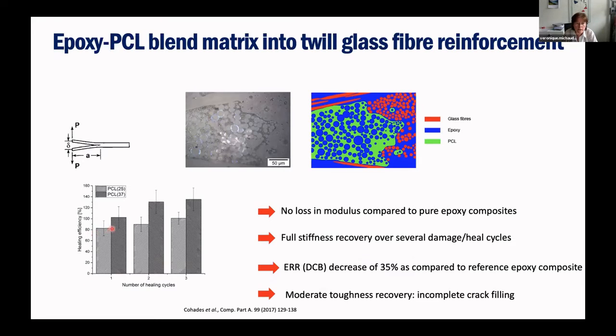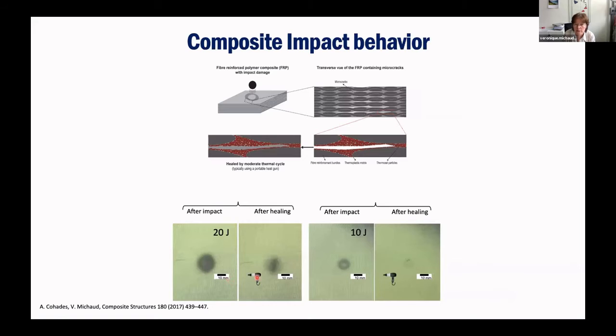But we had some healing efficiency in terms of the stiffness recovery in particular. It worked actually quite well. So we were fairly happy with this. We saw that there were some problems, but we managed to do some publication anyway. This was in 2017. So then we said, okay, because we have a hard time to fill the cracks, a DCB test, in fact, is not representative of what you have in real cases.